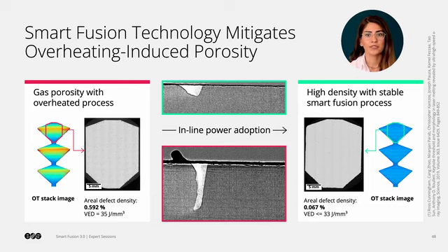If we compare OT stack images of these two samples, we see a high variation in radiation intensity from the sample made with the high volume energy density. This actually shows us that we have an inhomogeneous thermal behavior and also some overheated regions as well. In contrast, the real-time laser adjustment with Smart Fusion results in a more uniform radiation intensity throughout the entire manufacturing process.